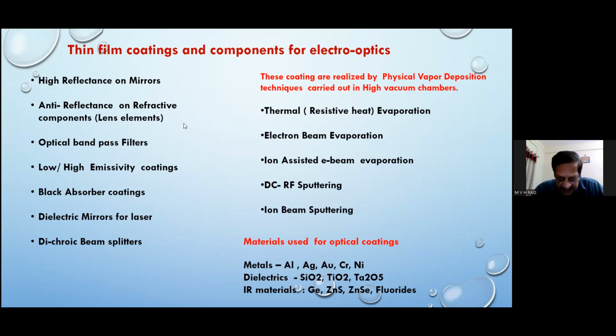So already I have covered this. Generally, typically the reflective coatings are done with aluminum, silver, gold, and chromium. These are the materials that are used for reflective coatings. For dielectric coatings, silicon dioxide is a low index material. Titanium oxide is a high index material. Tantalum oxide is also a high index material. Generally, most of these filters are done with multi-layer high and low refractive index coatings. And by appropriate optical design of the coatings, they are realized.